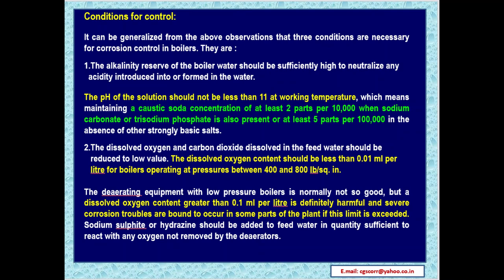The dissolved oxygen and carbon dioxide dissolved in the feed water should be reduced to a low level. The dissolved oxygen content should be less than 0.01 ml per liter for boilers operating at pressures between 400 and 800 pounds per square inch. The deaerating equipment with low pressure boilers is normally not so good, but a dissolved oxygen content greater than 0.1 ml per liter is definitely harmful, and severe corrosion troubles are bound to occur in some parts of the plant if this limit is exceeded.